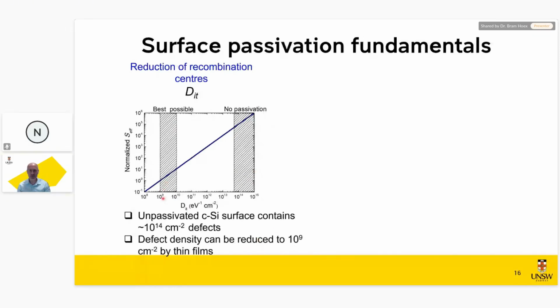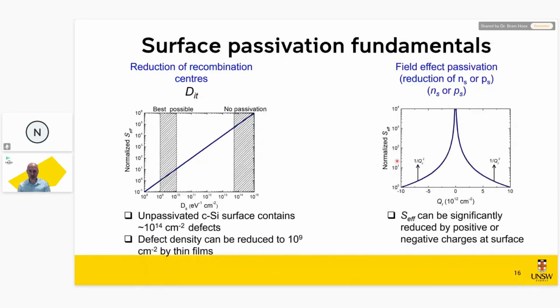The best we can achieve is 10 to the 9, and that's with thermal oxide. This was used in the UNSW world record PERC cells in the late 90s. But the typical AlOx film is in this range, so like 10 to the 10, 10 to the 11, because most films also rely on the second part, which is field effect passivation, where you have fixed charge in your dielectric. Either a negative charge or a positive charge can reduce recombination, because for recombination you need both an electron and a hole. If one of them is in short supply, then your recombination rate goes down. So with negative charge, you push away the electrons, and that reduces the recombination with the electron concentration.